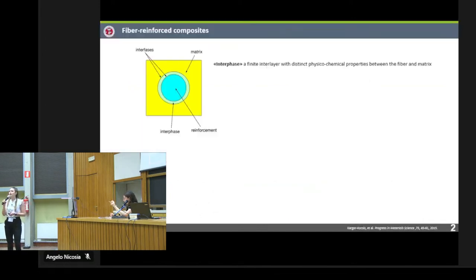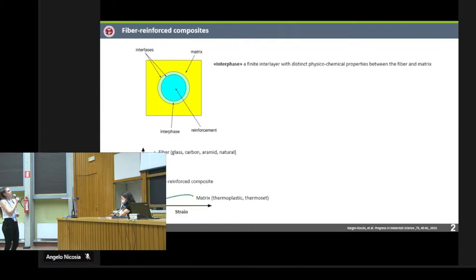So we know that a fiber-reinforced composite is made of matrix and fibers, and between these two there's a region called the interface, where matrix and fibers can interact. Fibers are much stronger than the corresponding matrix, so it's very important that when a stress is applied to the composite, the matrix transfers this load to the fibers. And this can only happen if there's a good interfacial adhesion between fibers and matrix.